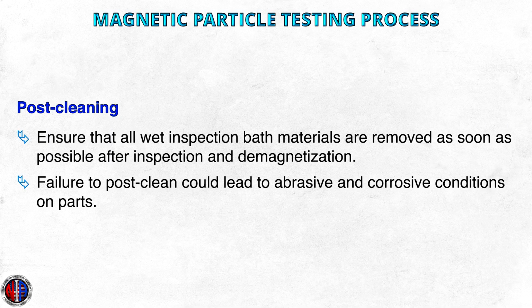Post-cleaning. To post-clean the test object, ensure that all wet inspection bath materials are removed as soon as possible after inspection and demagnetization. Failure to post-clean could lead to abrasive and corrosive conditions on the part.